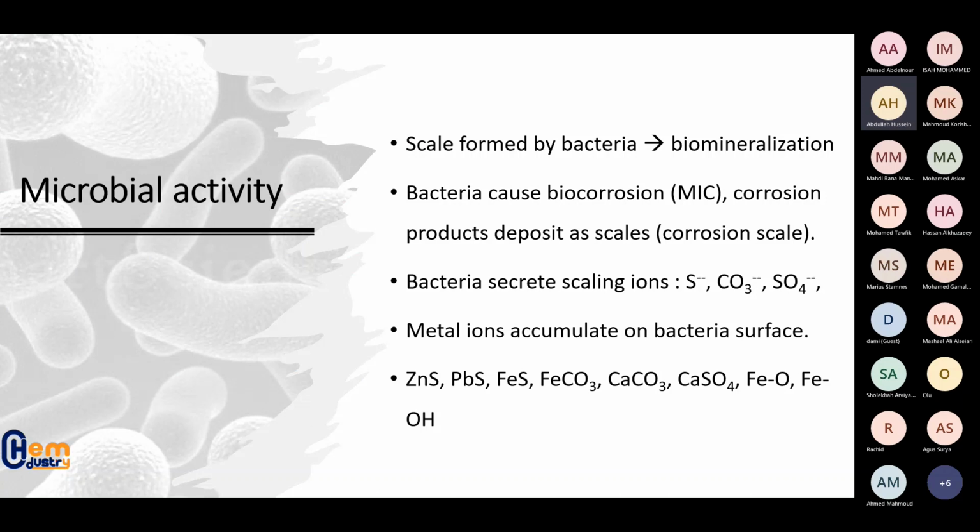And then we have another factor, which is the microbial activity. Bacteria not just can cause microbial corrosion, they also can cause biofouling. And whenever they cause scale formation, it is called biomineralization. The biomineralization can happen in so many different ways. The common one is the biocorrosion.